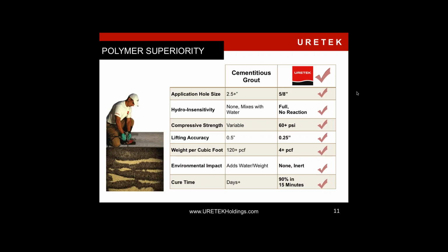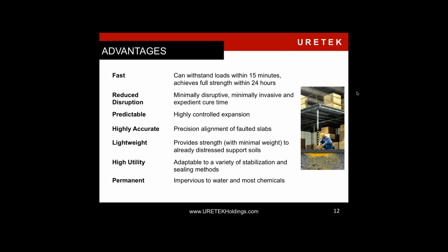Also, the material is much lighter than cementitious grout. And once the cementitious grout sets up, it will shrink. There will be some shrinkage due to the water drying out. Also, your cure time: days versus a few minutes. Again, recapping on the advantages: setting up so quickly, 15 minutes, minimal disruption of traffic, able to control the expansion of the material, being able to bring slabs back into alignment, and your strength-to-weight ratio far exceeds anything else. And it's also impervious to water and most chemicals.